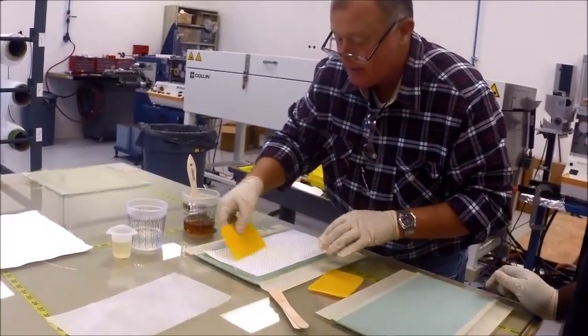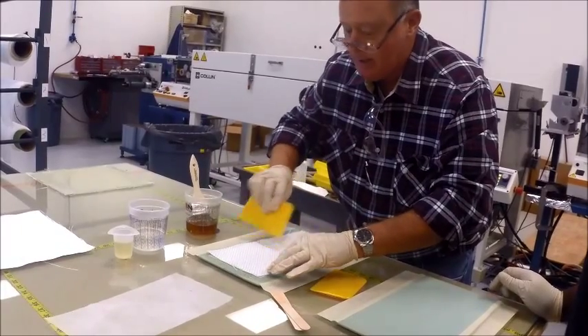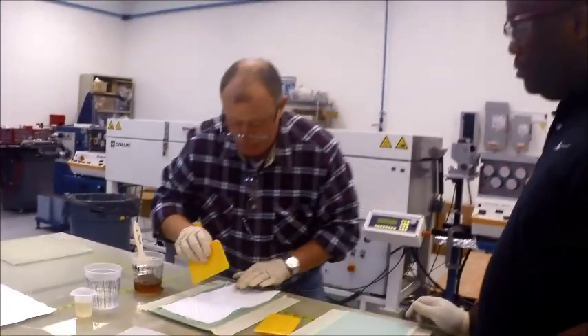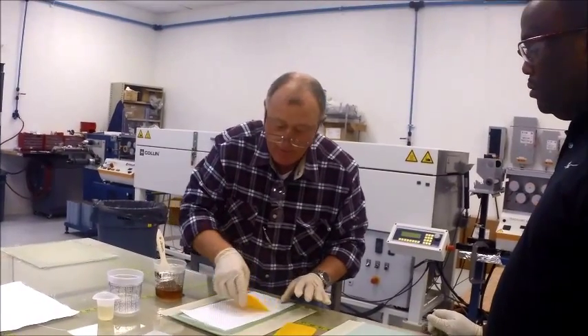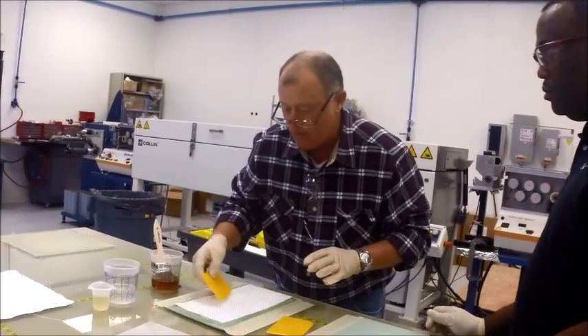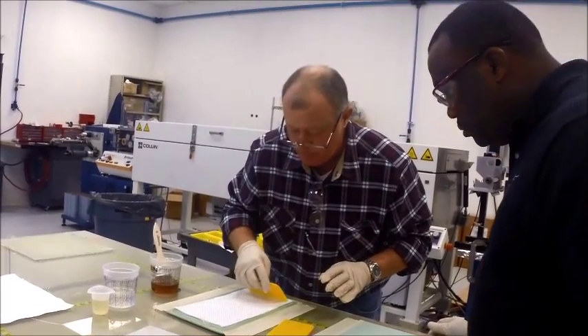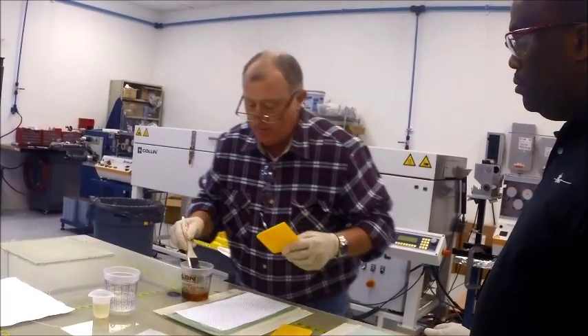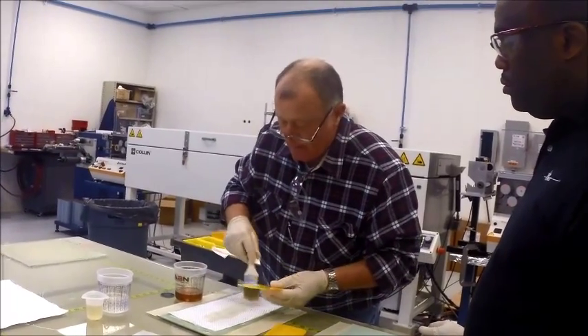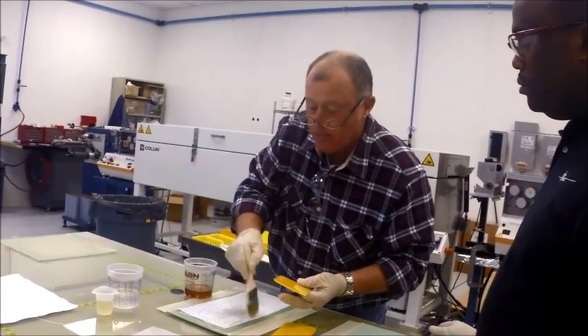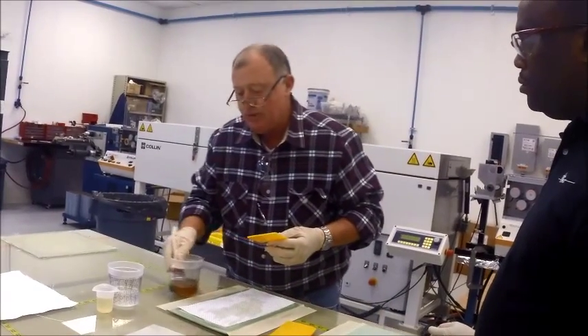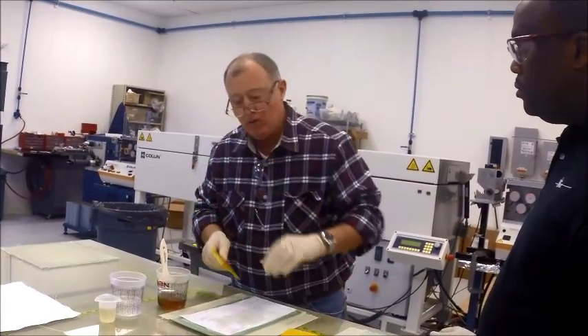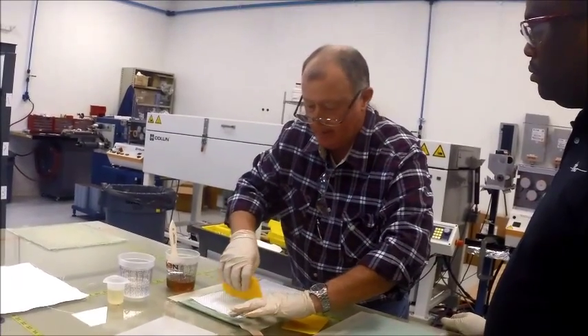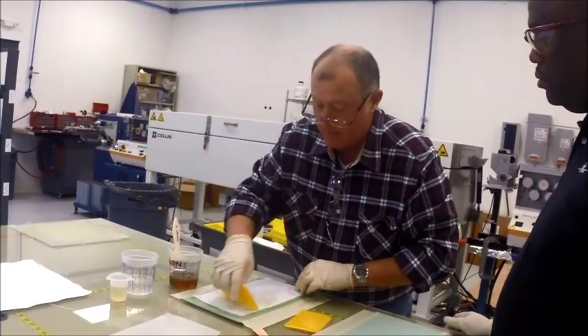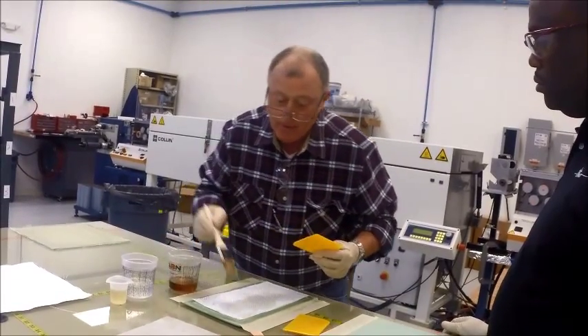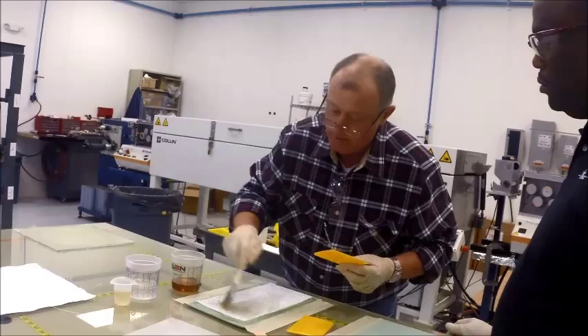Lightly tack this down. Now Innegra's got enough body that if you're careful, you can control the actual fiber alignment. So if you're trying to get a particular type of pattern on the top of your board, Innegra will allow you to do that. A lot of times glass, carbon, aramids are so soft and supple that they're very difficult to control without putting a backer on it or a stabilizing material on the back. Innegra does give you an advantage in that regard. Again, what we're going to do is wet it out and then squeegee her down.